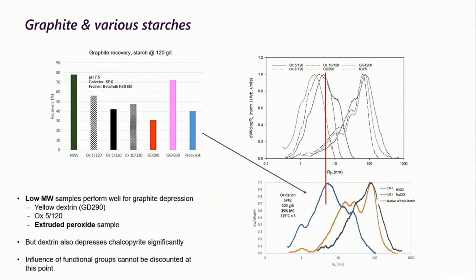After doing that, we thought we'd try a few other starches. So of just native wheat starch, there's the three I just talked about. That pink one there is an oxidized commercially available starch from Manildra, and also a dextrin. Now the dextrin and the blue one there is an extruded starch, which is what we're trying to produce. So one thing we're trying to do is find out what structures work, and then once we establish that, we want to use reactive extrusion to mass produce these things, moving from the solution chemistry that's usual to a continuous mass production via extrusion. So the fact that we're able to produce, in this case, the blue down on the right there, a 1% peroxide oxidized starch with a molecular weight that's pretty much in the range of the one that worked for the Ox5 120, looks promising.